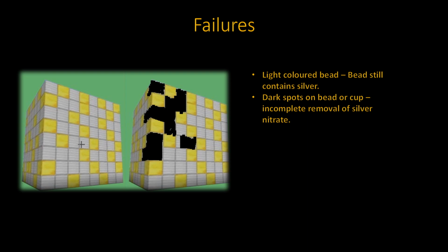As mentioned during parting, silver nitrate will be the product that is decanted. However, if the parting has not been fully completed, some silver nitrate will still be present. This will show up as dark spotted areas on the bead, as well as a stain on the parting cup. Gold is slightly soluble in highly concentrated nitric acid. Loss does occur if the acid solution is highly concentrated. Never use concentrated nitric acid for parting.